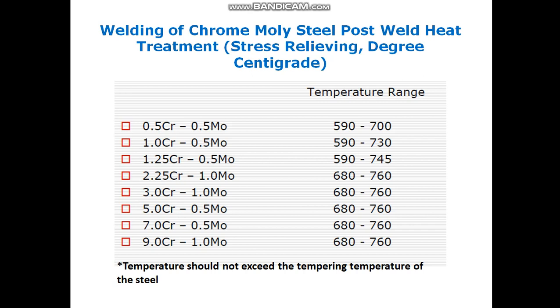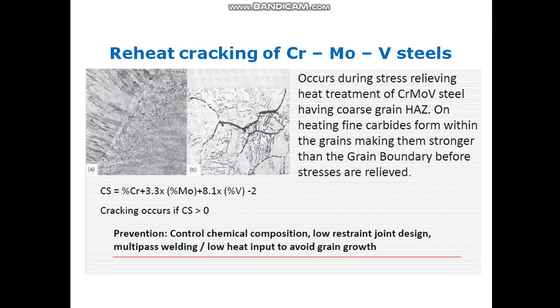If the temperature range crosses the tempering temperature, then we don't get the benefit of the strength. Because these materials are air hardening in nature, the moment they cross the lower critical temperature, they transform back to austenite, and with a conventional cooling rate in still air, they obtain hardness and their properties will be deteriorated. In subsequent slides, we will try to understand this phenomenon.